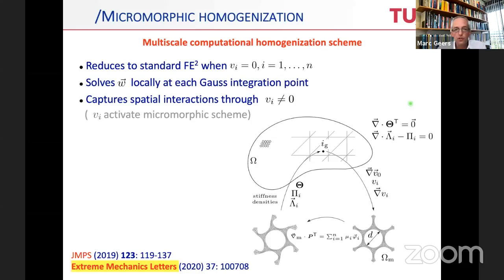So in the multiscale computational scheme, it then looks like this. We have a macroscopic problem. We have the standard balance equation, the additional balance equation. The quantities that have to be transferred from the macroscale to the microscale are the standard gradient of the mean field displacement, the amplitudes of the modes, and the gradients thereof. Once that's done, the microscale problem can be solved and the corresponding stress quantities and stiffnesses are returned back to the macroscopic scale. So whenever these modes are zero, which means there is no pattern, you will recover a standard FE squared, which is standard computational homogenization.